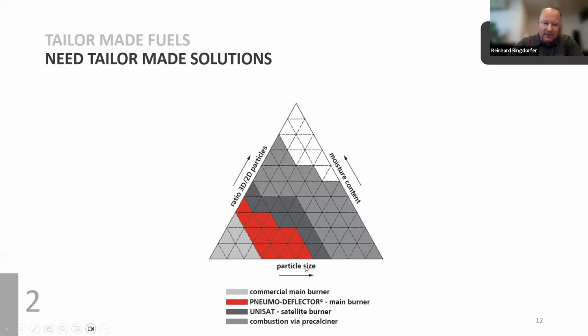So here you can cover a little bit bigger area. The next step would be the satellite burner, where we still have a little bit more freedom in regards of size or humidity or moisture of the particles. And the rest, which was also explained earlier, is combustion in the pre-calciner, because you don't need a really defined flame in the pre-calciner. You just need to release the heat, not at a specific point. And of course, also you have a higher retention time in the calciner.